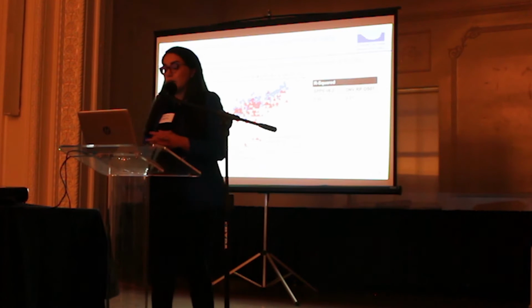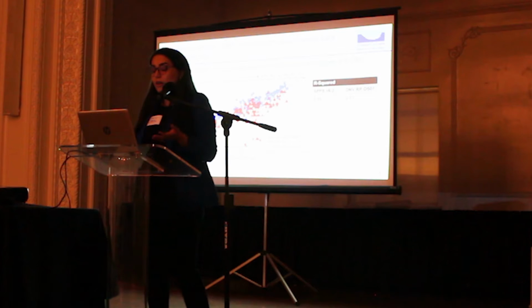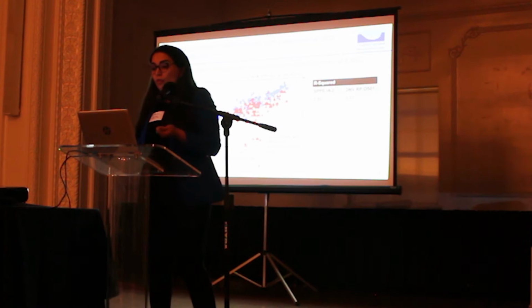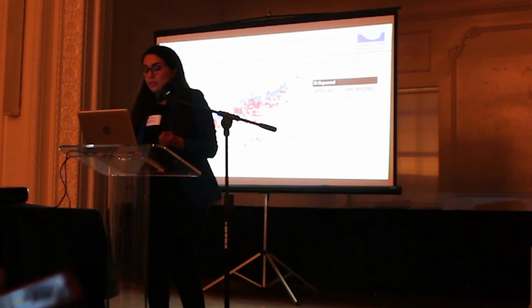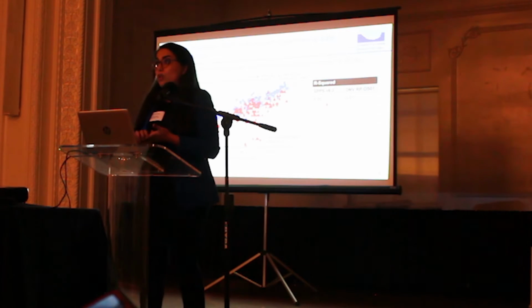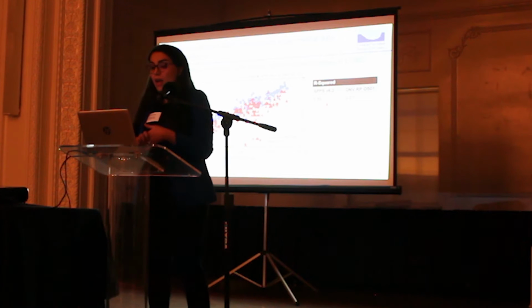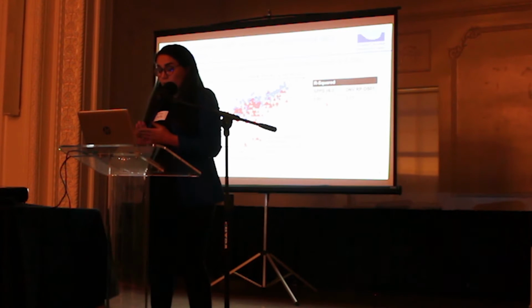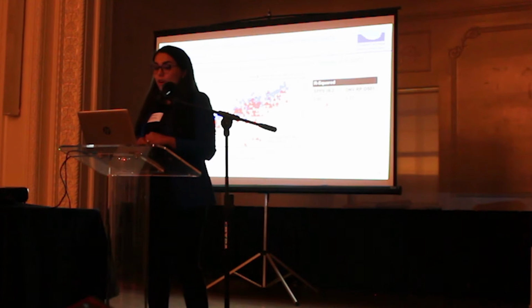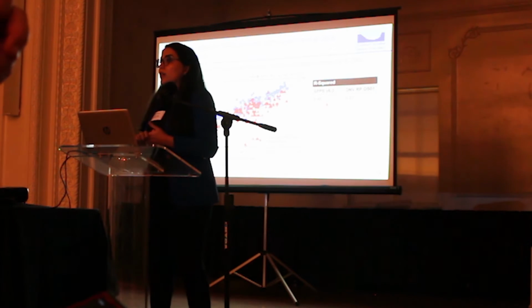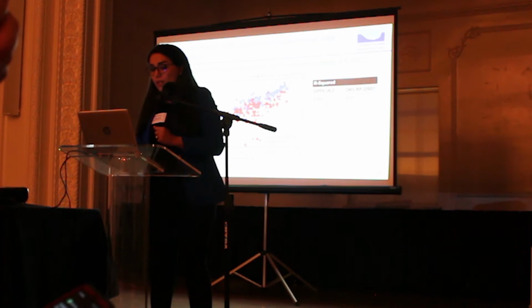And another example, like API is not the only thing that is out there. Another practice is DNV implemented practice. In this slide, we are looking at the predicted erosion versus the experimental erosion for large-scale erosion tests for stand-up elbows. And the blue dots or symbols show our software SPPS version 6.2 results compared to DNV results. And you see that our R-squared values are much higher. So we have developed better models and software to predict for these conditions what we see in the experimental data.